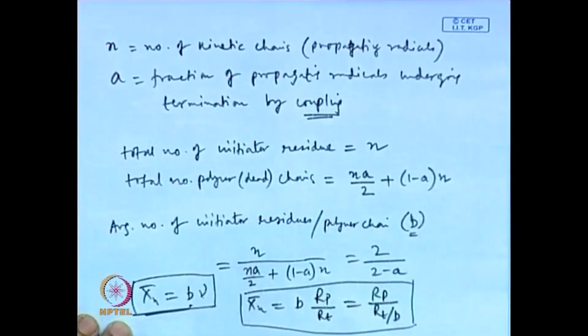So, this is the average degree of polymerization, we can get it from this, unless the monomer is sterically crowded. If we are talking about a coupling reaction, then two radical chain ends have to come and collide with each other. Unless the monomers are sterically crowded or have an easily abstractable beta hydrogen, in the majority of cases they undergo termination by coupling reaction, like styrene, acrylonitrile, methyl acrylate.